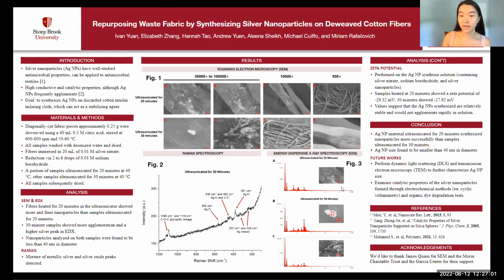negative 27.92 millivolts. These relatively high negative zeta potentials indicate significant electrostatic repulsion amongst the silver nanoparticles, which prevents agglomeration, and we observed this especially in the 20-minute sample. Lastly, Raman spectroscopy revealed peaks associated with cellulose, silver metal, and silver oxide, as shown in figure 2. In the future, we'll perform dynamic light scattering to further characterize the size of nanoparticles.